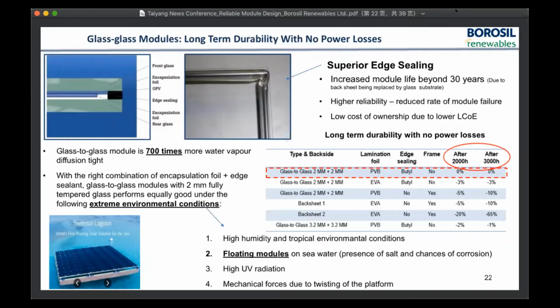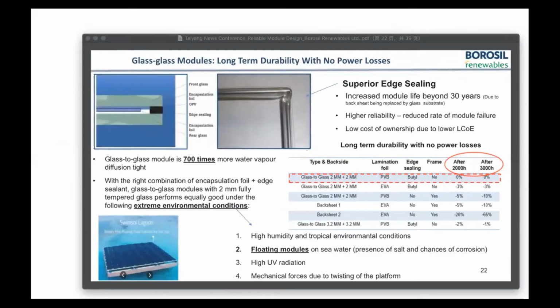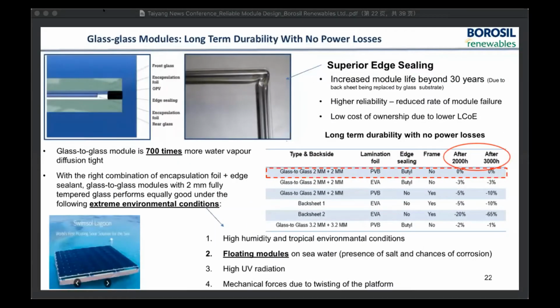There is a high reliability, so less module failures, and also considering the overall design, the low cost of ownership due to lower BOS as well as the other costs. When it comes to why we say the durability, it also has got to do with the degradation. Some tests were done, and if you use 2 mm glass module with a proper edge sealing as well as the lamination foil, the degradation is the minimum.